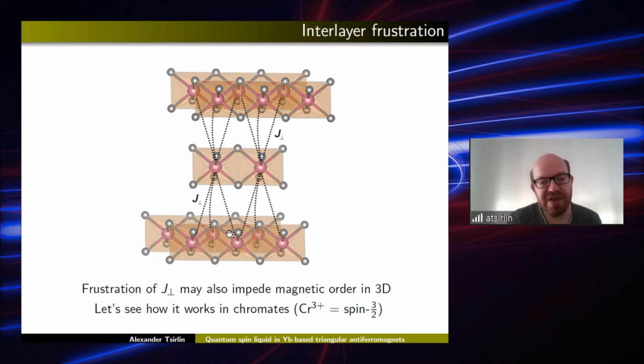And in fact, this is a very common situation that you encounter in many different types of layered materials. But I think it's still not so clear how it affects the magnetic order, especially when you have the triangular planes and the frustration. And we tried to see it by going to the more classical system, to the chromates, which can also form the same type of crystal structure, because then we kind of remove the quantum effects. We do not expect really a spin liquid, but we can just see how this interlayer frustration impacts magnetic order.